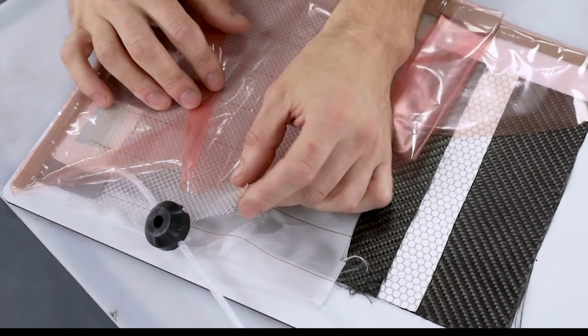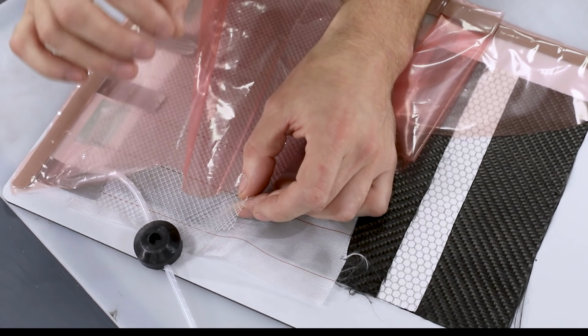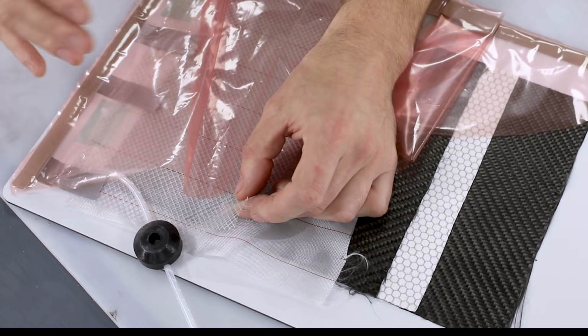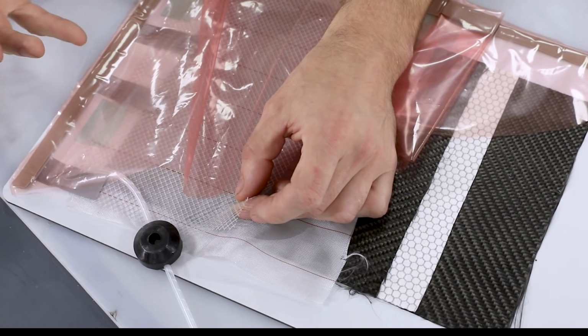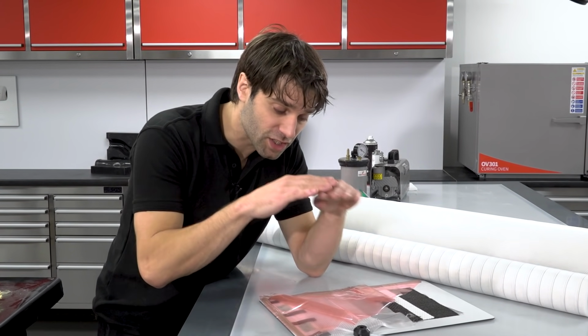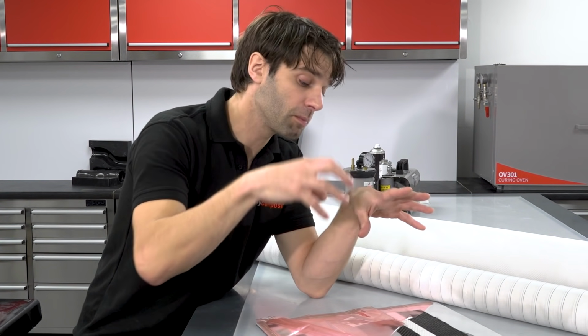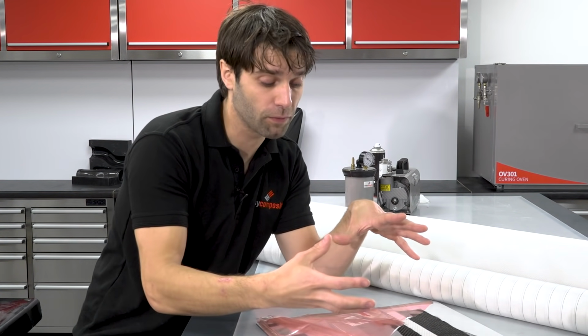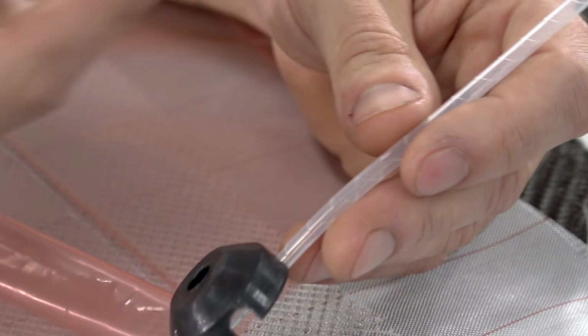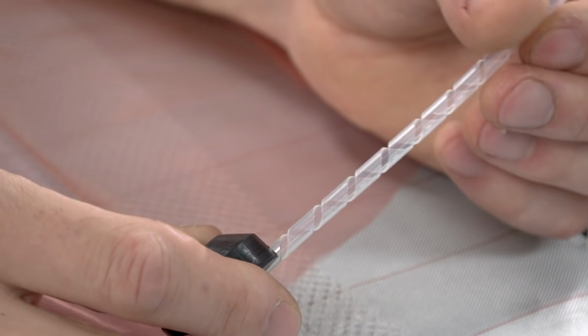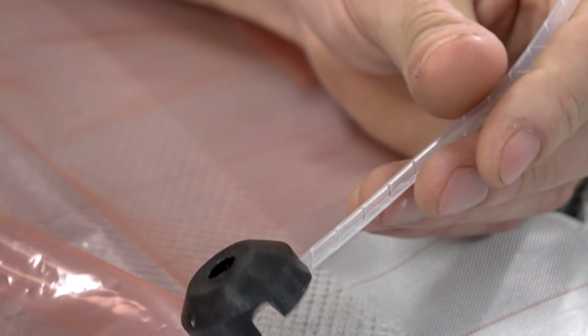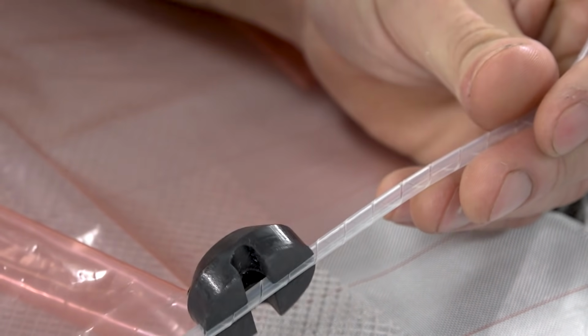So the infusion mesh then, that's the next layer in, and this is the material that allows the resin distribution. Without this, resin infusion really can't take place. And it works by creating channels with the bag bridging over the top, creates channels that the resin can flow down before flowing through the peel ply and into your reinforcement. To get the resin into that mesh, we're going to use a resin infusion spiral. Now this is essentially just a tube with a slit cut in a spiral fashion. So the resin will flow into that, down it very, very quickly, and then leak out through the spiral and into the mesh.